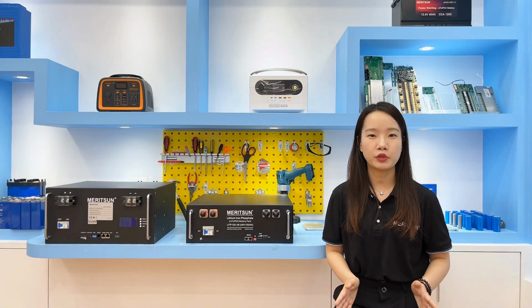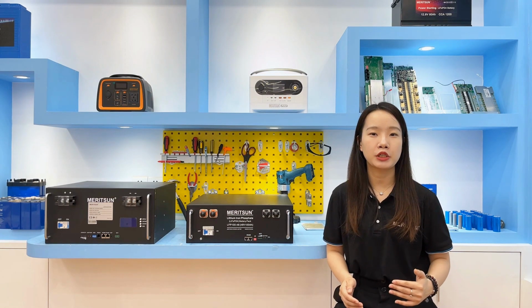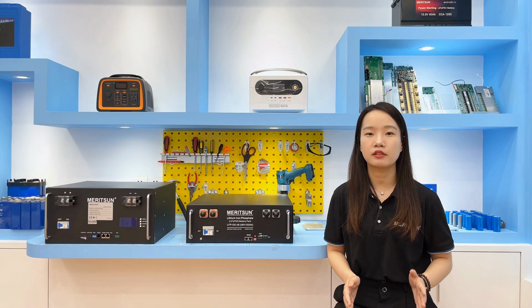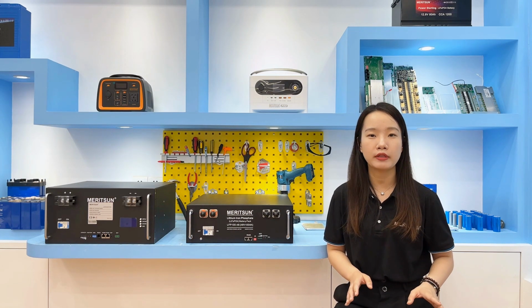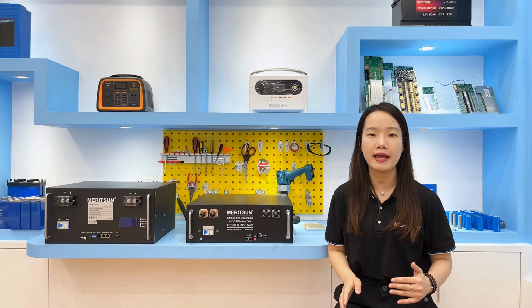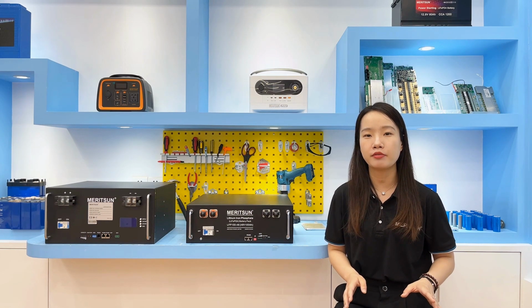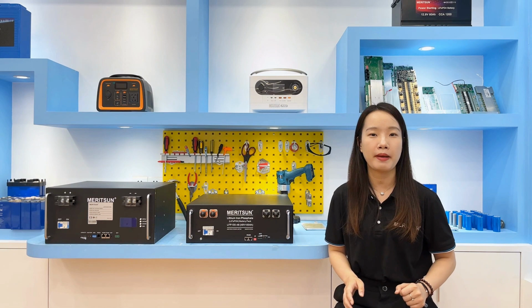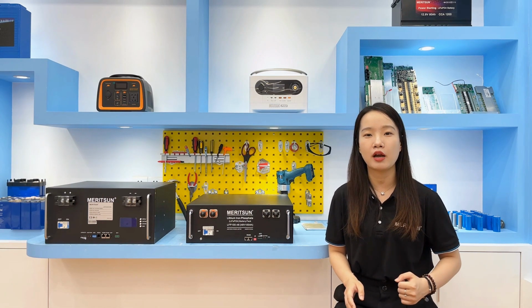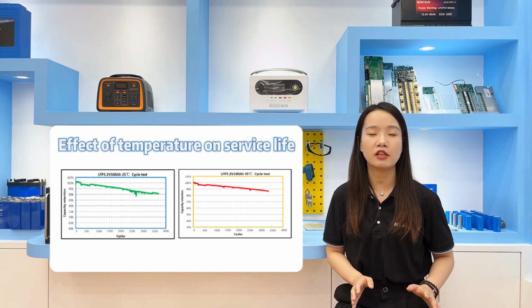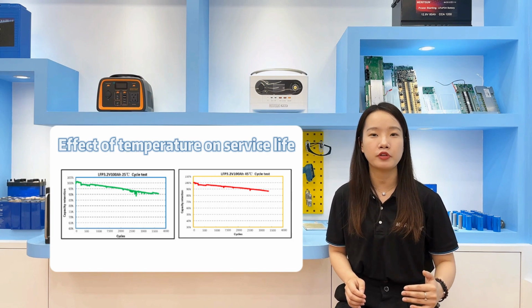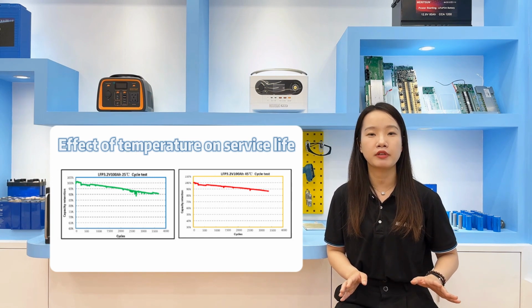The lower the temperature, the slower the ion migration rate, the more polarized the batteries, the more degraded the performance of the batteries. At the same time, charging at too low a temperature can easily lead to lithium plating, which can affect the safety of the battery and cause great damage to the batteries, so we need to avoid low temperature charging. The following data are used to illustrate. For example, a certain type of lithium iron phosphate battery is charged and discharged at 25 degrees and 45 degrees. The retention rate of the capacities will be different after 1,000 cycles.